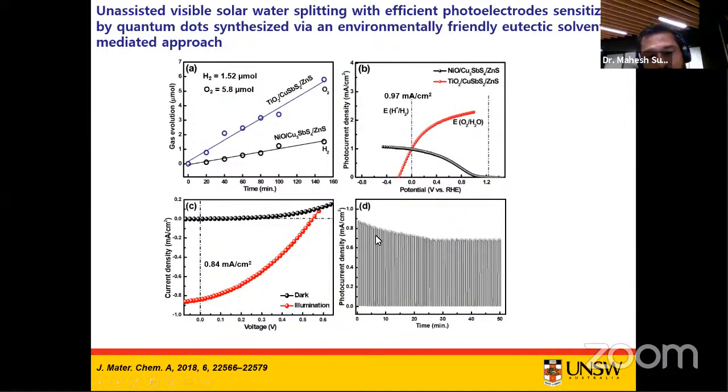The not-so-promising stability can again be improved by putting the catalyst on top of the zinc sulfide passivation layer, or by simply replacing this zinc sulfide passivation layer with different compounds, such as phosphide-based, oxide-based or hydroxide-based compounds. Again, it highly depends on the band alignment between the Cu3SbS4 copper antimony sulfide and the upper layer that we are going to use.